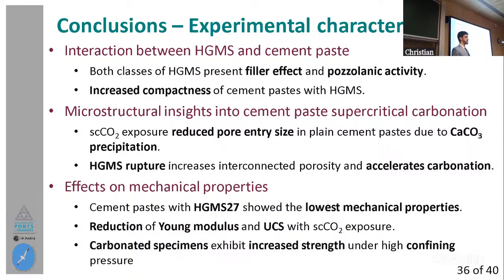Initially, we have seen that the spheres already affected quite a lot the mechanical properties, decreasing the unconfined compressive strength and Young modulus. And then we have some reduction in these unconfined mechanical properties due to carbonation. And finally, we have seen an increased strength, increased frictional behavior of the carbonated specimens after carbonation.